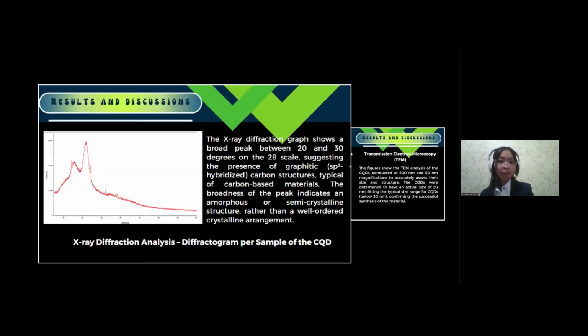Next, we have the X-ray diffraction analysis. The graph shows a broad peak between 20 and 30 degrees on the 2 theta scale, indicating the presence of graphitic carbon structures. However, the peak's broadness means that the material is mostly amorphous or semi-crystalline, not a well-ordered crystal. This suggests that the CQDs made from pomelo peels are mostly amorphous with some graphitic regions, which matches the TEM images